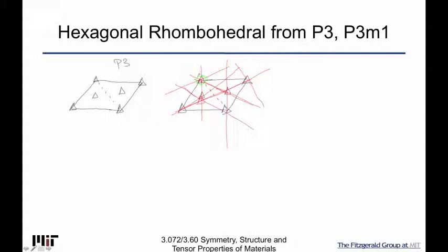And therefore this one can, in the last case, be sitting above itself in P3, or I can go now to this one. And the same thing here. This is the same as this. It has lower symmetry. It doesn't have all these mirror planes, but it can go that way. Now you might ask, well, okay, they're all the same. I've got this one and this one. And that's correct. This is a distinct one, because remember, this dashed line is not really anything. There is a unique direction here and here. However, what you'll see is if you rotate this 180 degrees, this is the same as this one. So it's not going to offer any different crystal structure. So we only need to think about two. We already talked about the hexagonal primitive, and so now we only need to do that one.